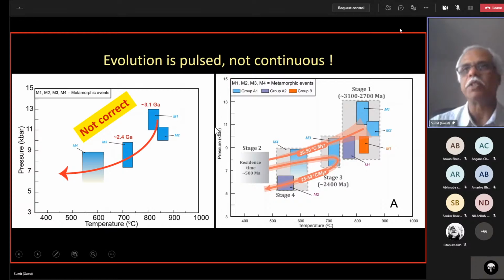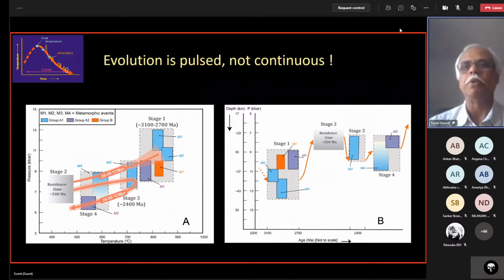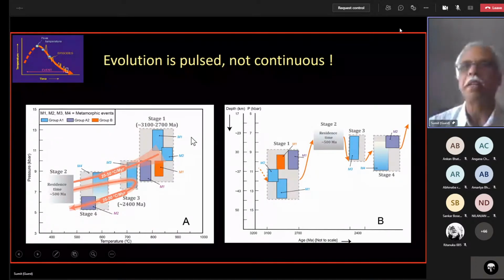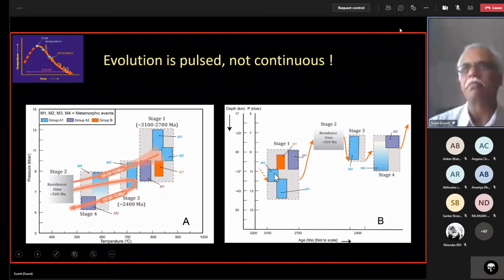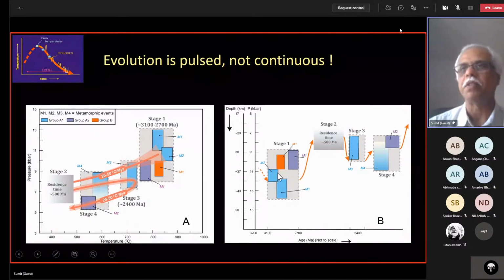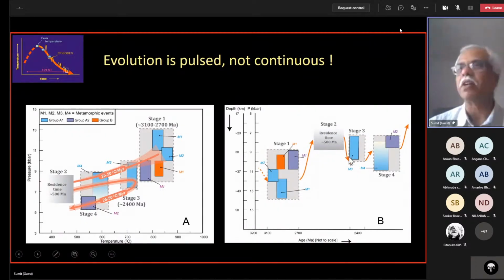So if you want to look at it in an image that you can relate to, you can look at depth against time. On the left, you have the same picture again, but on the right-hand side, you see pressure or depth as a function of time. And you have this initial stage, considerable uncertainty, but that's where we were about 3,000 million years ago. That was followed by some exhumation, not all the way to the surface most likely, but somewhere at lower temperatures and pressures. And then it got heated and buried, a little bit buried, but heated mostly, to the second stage, and finally got exhumed.